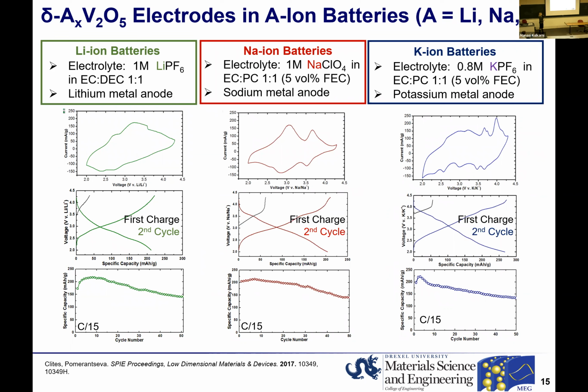So these results triggered us to investigate the mechanism of charge storage. So what we've done, we synthesized lithium, sodium, and potassium pre-intercalated bilayered vanadium oxides and cycled them in lithium-ion, sodium-ion, and potassium-ion batteries. And from the shape of the CV curves, one can see right away that the mechanism of charge storage is different in the case of these three systems.